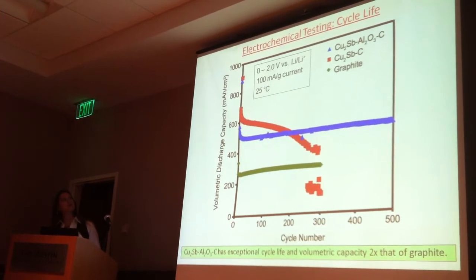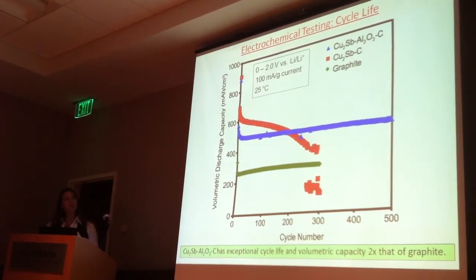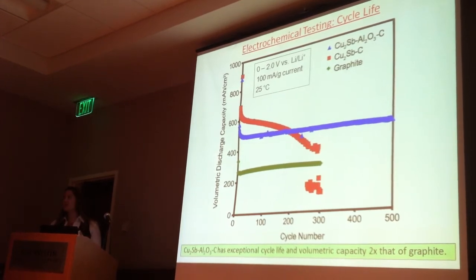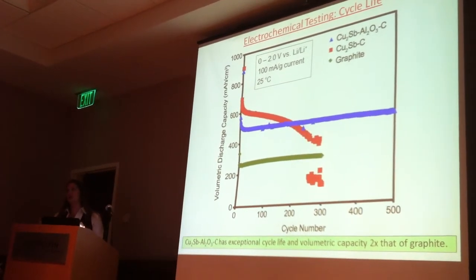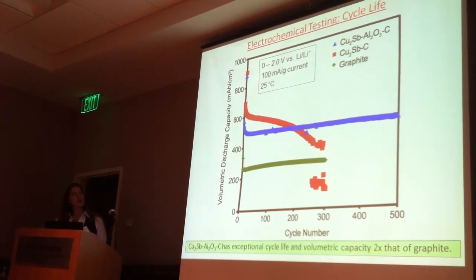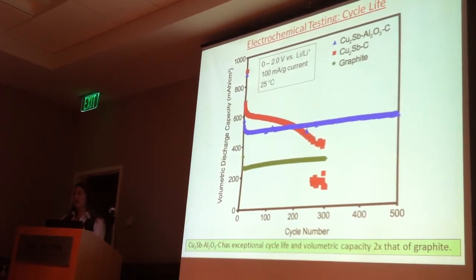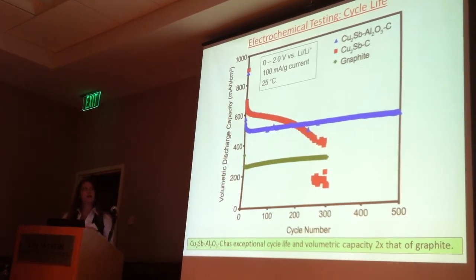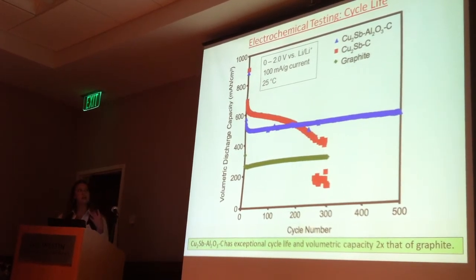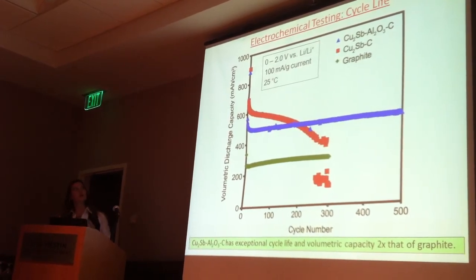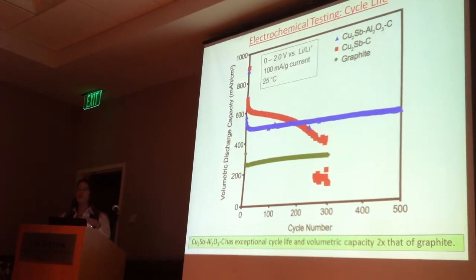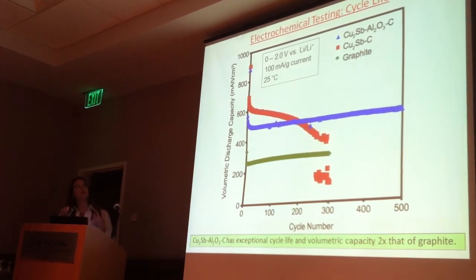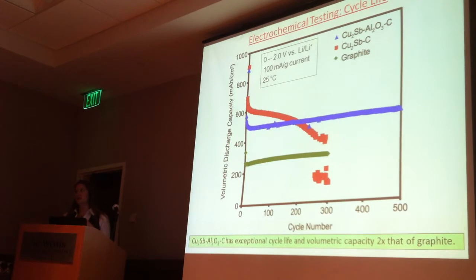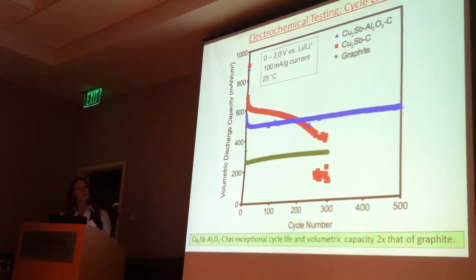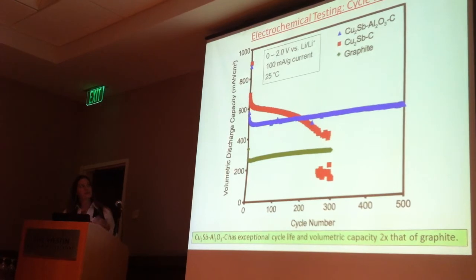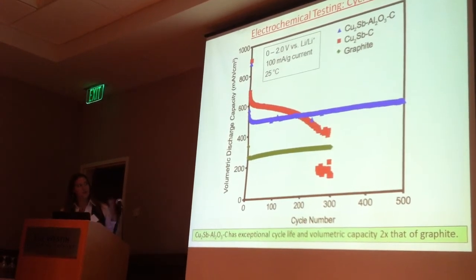Just a note, the current measurement that I have here is not in terms of C rate. That's because in order to calculate C rate, you need to know the theoretical capacity for your material, and we had variable amounts of carbon. We weren't sure how much that carbon was contributing to the theoretical capacity for our material. So instead of arbitrarily choosing a C rate, we decided to just do 100 milliamps per gram of composite material, and that's the entire composite, Cu2Sb, aluminum oxide, and C, just to clarify what our charge rates are. So you can see 500 cycles, stable.